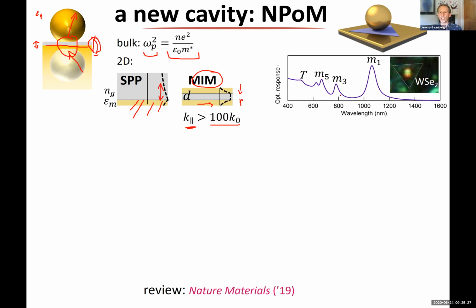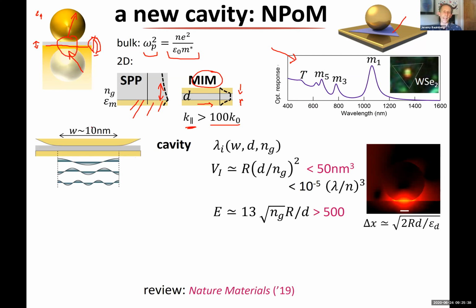But when we look at such structures, if we look at the spectroscopy of a structure like this, so we put a TMD in the gap here, then we see actually a number of different modes. That's not what we would expect from that. The reason that we get that is because whenever we put a nanoparticle down, we always find this nanoparticle is faceted. So it doesn't matter how superspherical it might be to start with, as soon as you put it down, the van der Waals interaction is extremely strong and it re-sculpts the bottom of the nanoparticle, and it's always a facet on the order of 10, 20 nanometers.